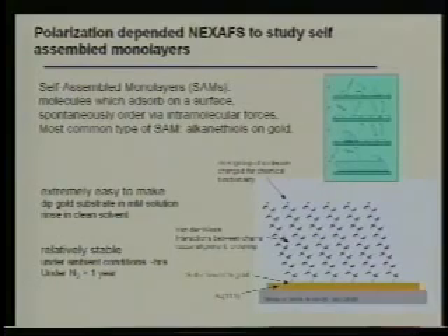So work that's being done in my group at Lawrence Livermore is we're looking at various types of self-assembled monolayers. And I'm not sure how much the group here knows about self-assembled monolayers. If we look at the diagram in the bottom corner, this is a self-assembled monolayer system, and it consists of, at the bottom, a sulfur group. And the sulfur group is usually bonded to a metal, in most cases gold. And then you can see that you have a fairly long alkyl chain, and at the top you can have a head group that has a different type of chemistry. And this is your typical alkane thiol self-assembled monolayer.